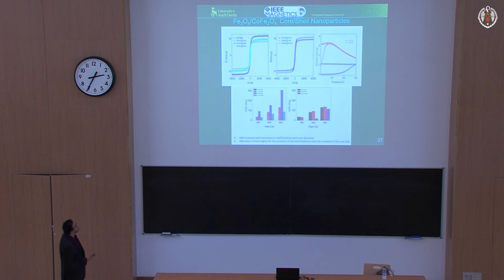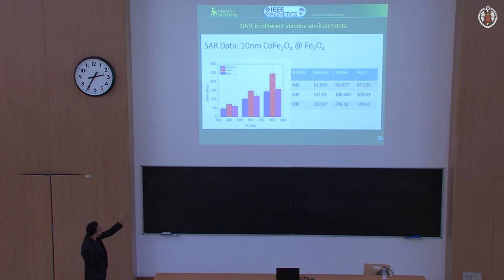So right now we are also doing this, cobalt again, but cobalt ferrite is inside and iron oxide is outside as a shell. The reason we use cobalt ferrite is because, as you know, among the ferrites, cobalt ferrite has the highest anisotropy. So we want to use anisotropy as a tool. This is something we want to look at. So these are some results we are getting. We do it in different environments to make sure that we have different conditions.